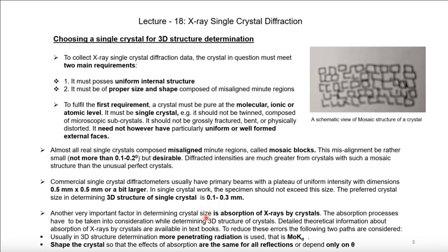And then another factor we have to consider: we know the crystal absorbs X-rays. So the absorption process should be minimized as much as we can. Otherwise, our intensity will reduce. To reduce this error, two parts are considered. One is that we have to have more penetrating radiation, and in this case molybdenum K alpha is the radiation we choose. The shape of the crystal we also have to take care of, so that all reflections have uniform absorption, or that it depends only on theta.